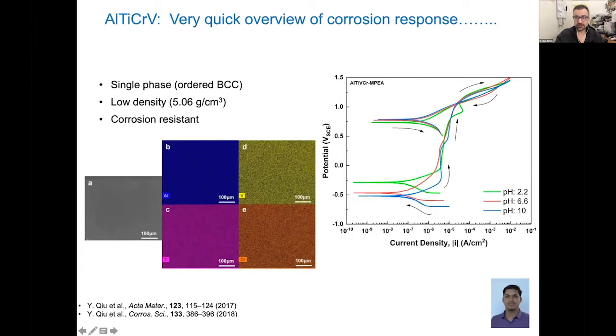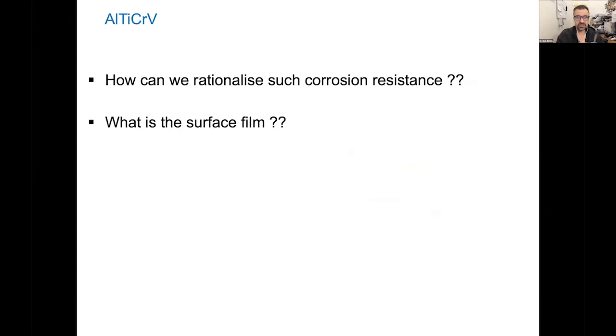And I'm not going to talk about the family of these aluminium, titanium, vanadium, chromium alloys because we've expanded into looking at the family. I'll just talk about this sort of archetypical alloy. But in spite of pH, very, very corrosion resistant, the hysteresis suggests very, very rapid repassivation as well of this particular alloy. So then the logical thing to do is to ask the question, well, how do we rationalize such corrosion resistance? And then subsequently, what is the surface film?